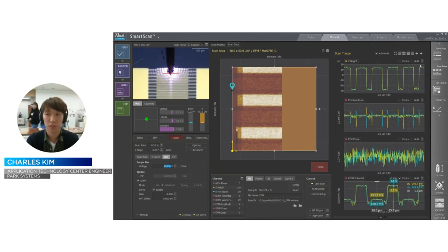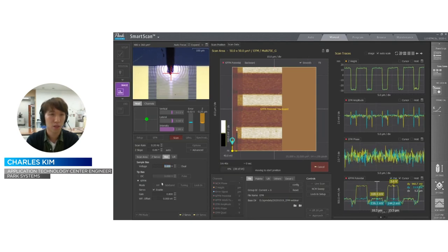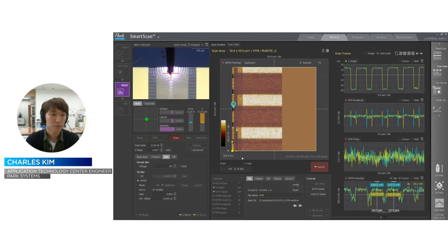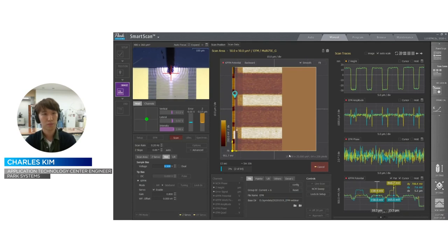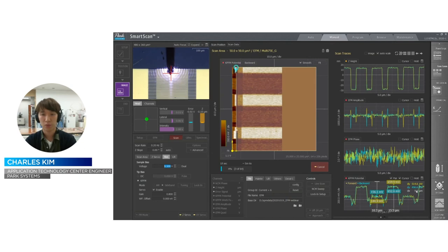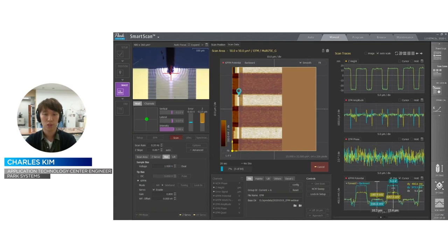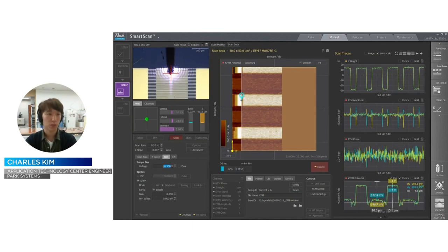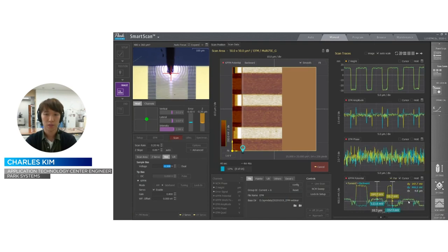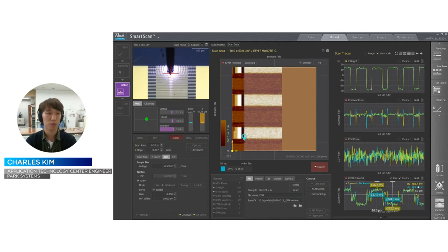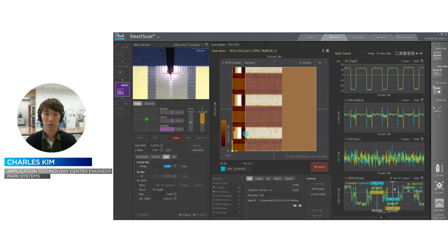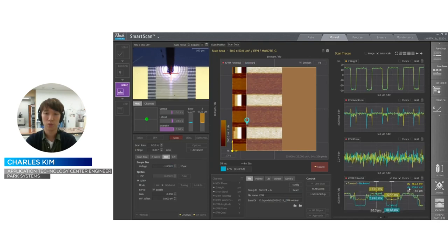So let's start the same measurement again. Then the values of the potential are 0.5 and 1. The potential value is almost close to 1 volt, like this, 999.8 millivolt. And if I change to minus 0.5, also the difference between grounded and the minus 0.5 electrode is 500 millivolt, and minus 1 is almost minus 1 volt like this.